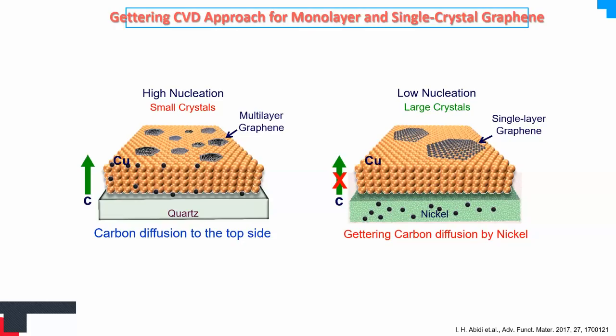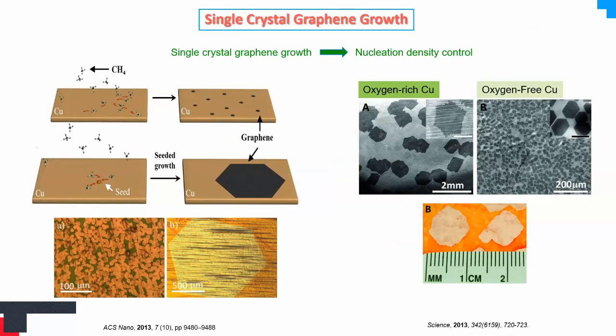This phenomenon actually happened accidentally with me, but it was very useful. So we grow this using this method. Of course, for single crystals, I want to mention there are other methods as well to control the nucleation density in single crystal graphene growth. The difference is you have to use some sort of seeding growth, to have only a few nuclei of the single crystals. The first paper on single crystal graphene used some oxygen environment to control the nucleation density of the graphene.